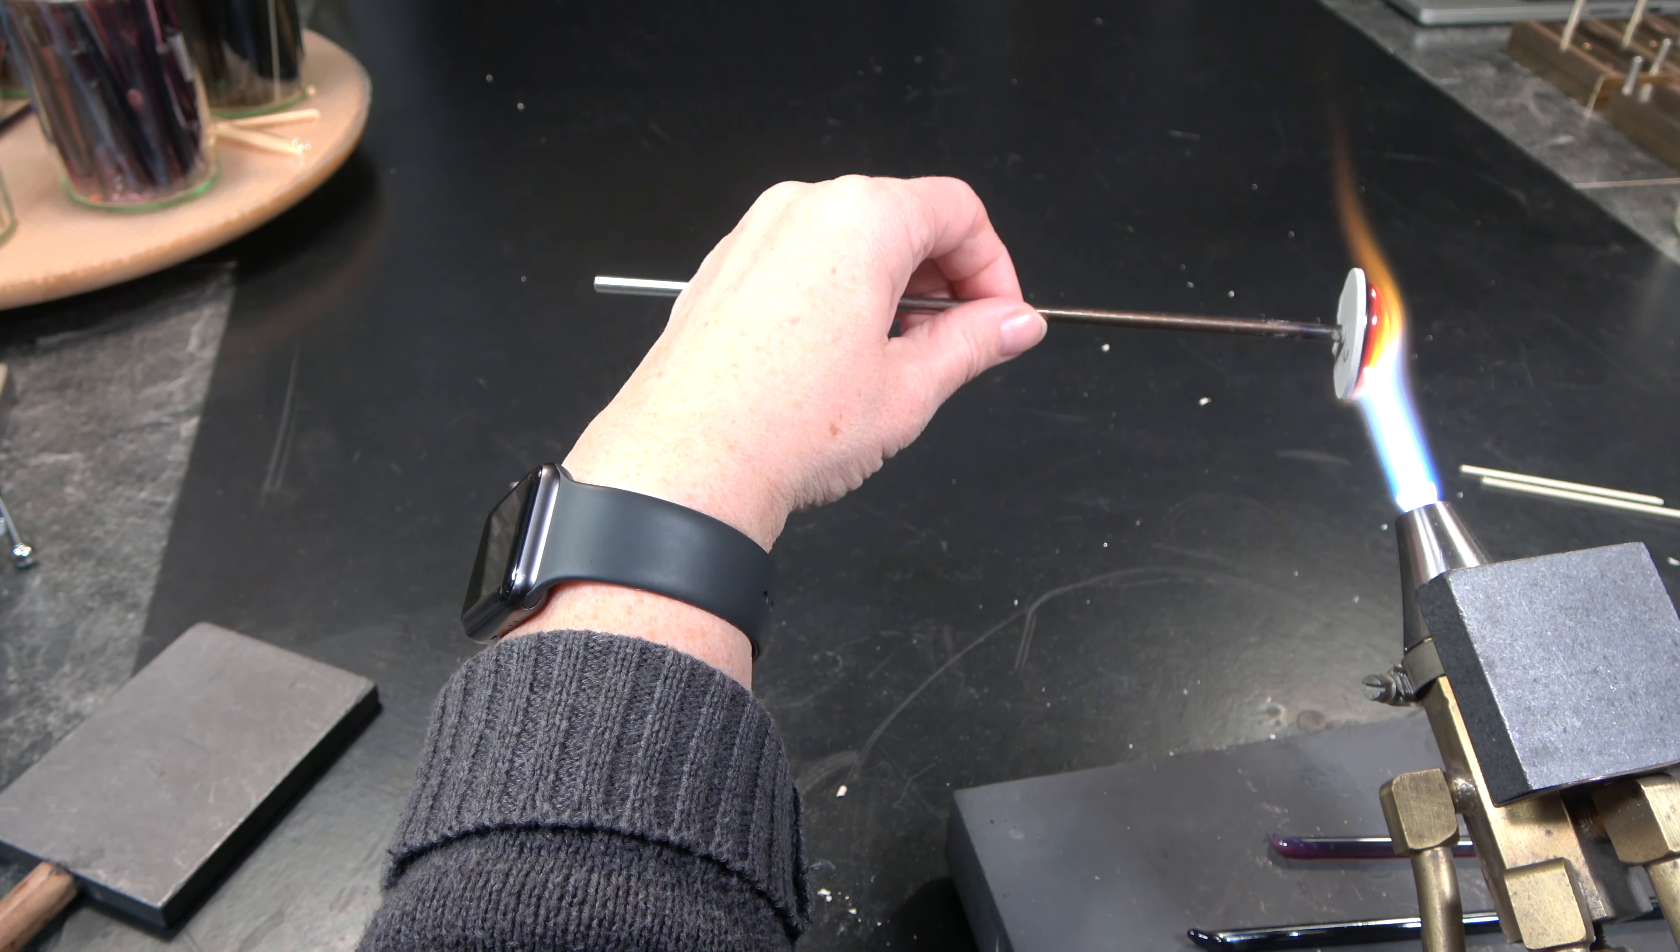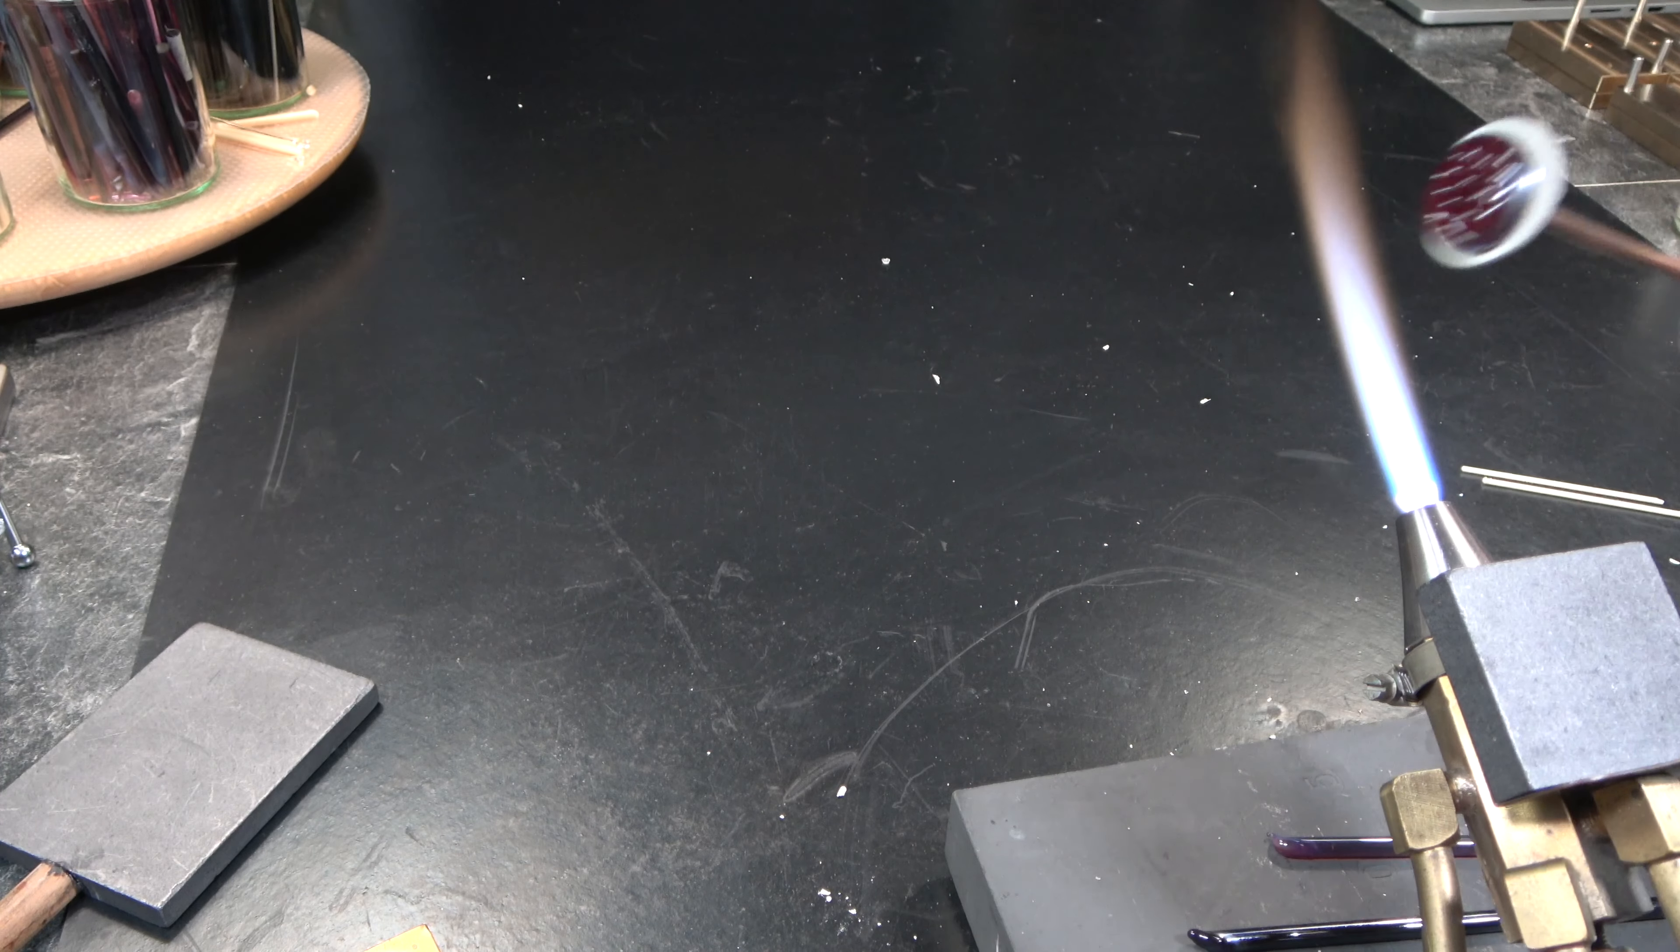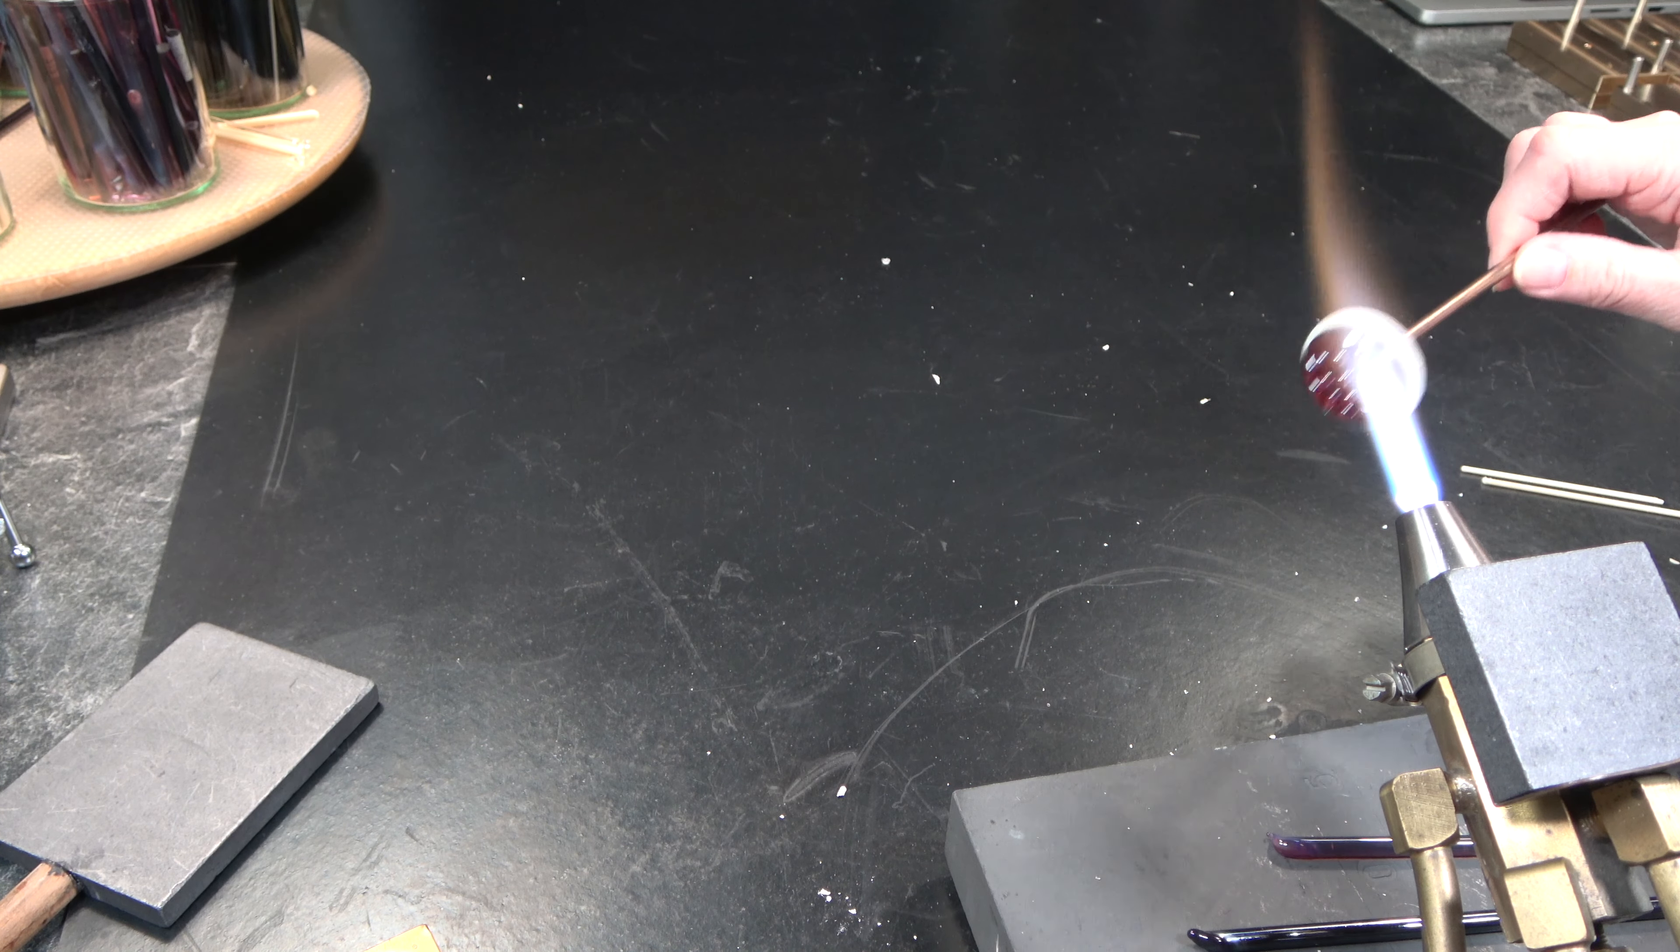Heat up the surface and shortly press in the stamp. If the glass is very hot and the stamp is warmed up from repeated use, it can happen that the stamp gets stuck when pressing it in for a bit longer. This is pretty rare though, and can be avoided by only pressing for short moments.